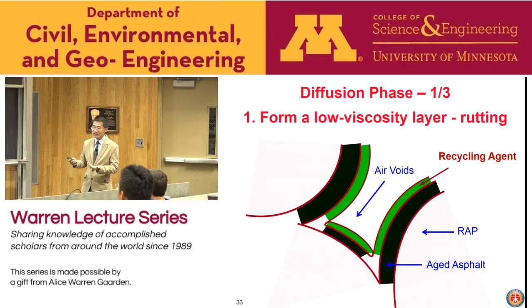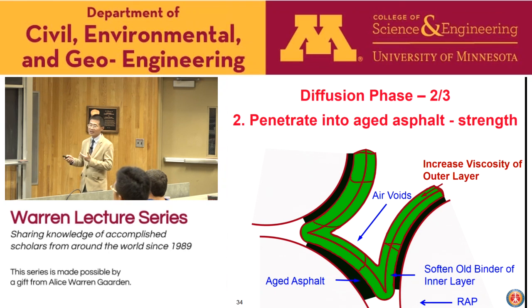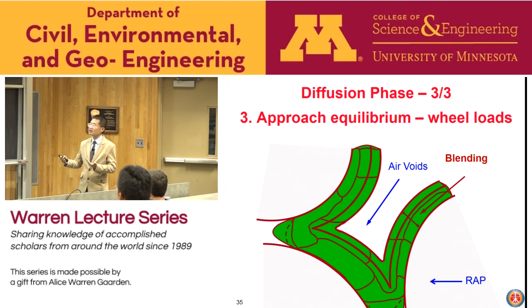Then gradually the recycling agent begins to penetrate into the aged asphalt, increasing the viscosity value of the outer layer here. At the same time, it also softens the inner binder layer. Asphalt mixture with high wrap content will start to develop strength and carry traffic loading at this time. Eventually, the rejuvenator blending will approach equilibrium here. So asphalt mixture with high wrap content will be able to develop sufficient strength to provide resistance to traffic loading, thermal cracking, or fatigue cracking. This is the final stage we want to have with high wrap contents.